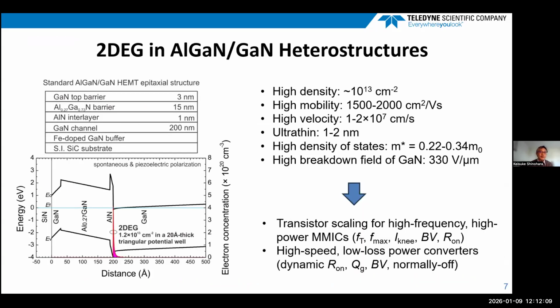So let's see the two-dimensional electron gas formed in aluminum gallium nitride heterostructures. Here I showed the standard AlGaN/GaN epitaxial structure grown on a silicon carbide substrate. As you can see in the band diagram, the 2DEG is formed at the aluminum nitride/gallium nitride interface. It is noted that the thickness of this 2DEG is as small as 1 to 2 nanometers. In this material system, without donor doping, a high electron density of 1e13 per square centimeter and high electron mobility between 1500 and 2000 can be obtained. The high velocity at high field and high density of states due to the high electron effective mass and high breakdown field of gallium nitride make this material system suitable for transistor scaling, for high frequency and high power MMIC application, as well as high-speed, low-loss power converter applications.